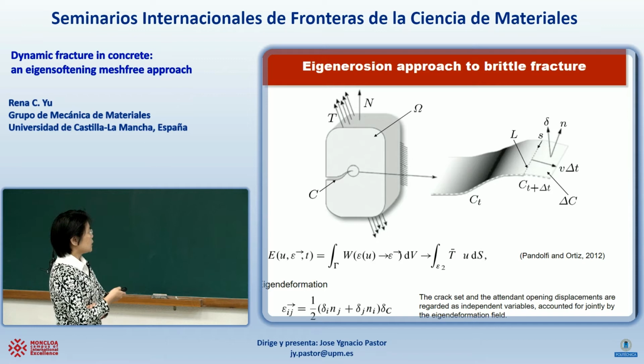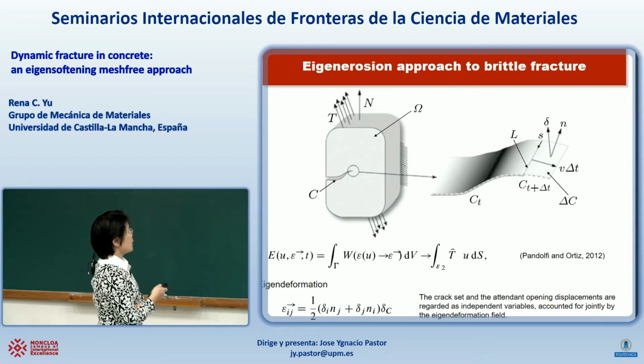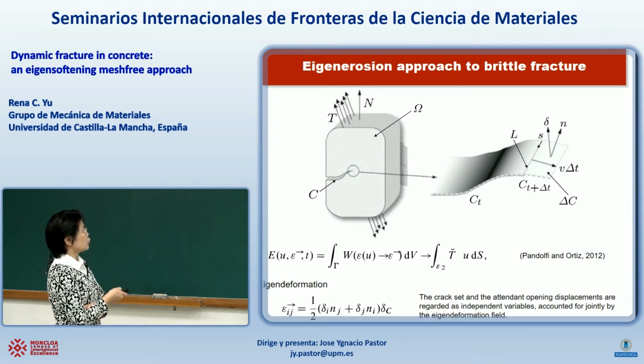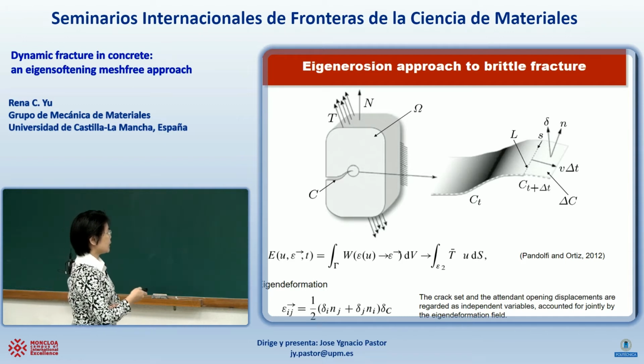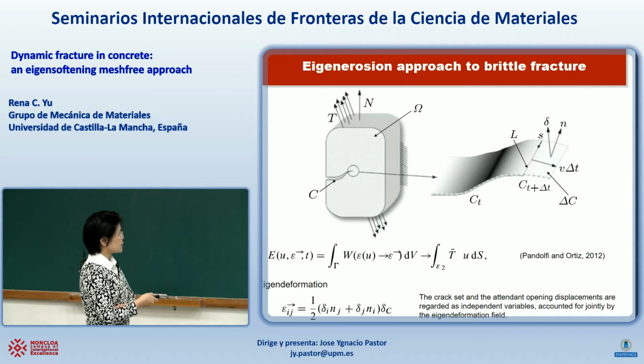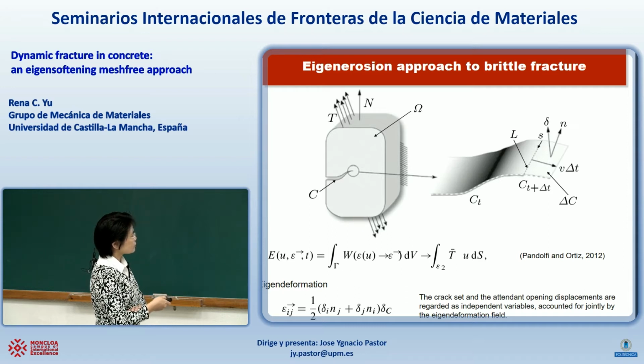So we start with the approach that was developed by Pandolfi and Ortiz in 2012, which is called the eigenerosion approach to brittle fracture. So the idea is that we have our 3D domain omega. This is the traction boundary condition. This is the crack set. And the zoom of this crack tip is that we have the crack front represented by L, and at time t plus delta t, the crack set has increased by this amount.